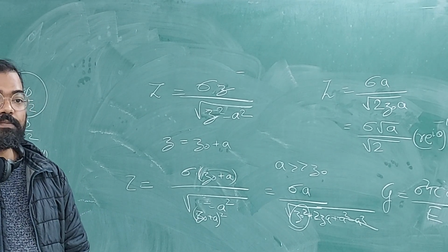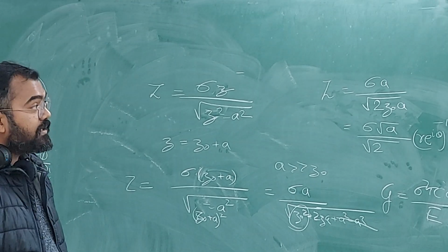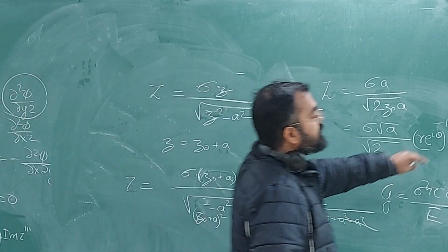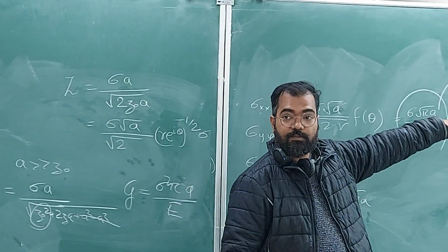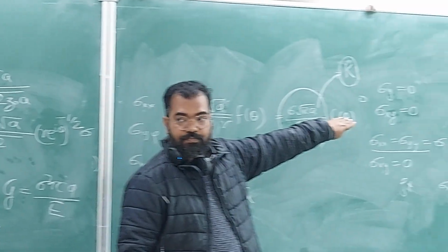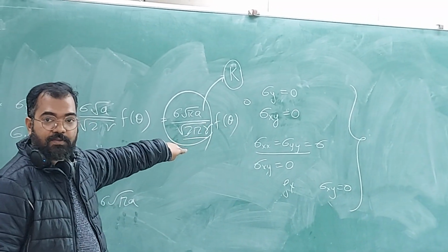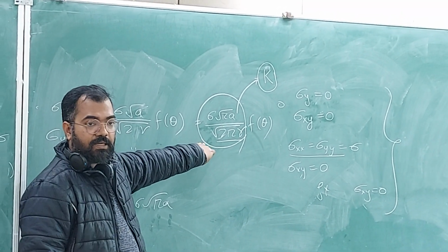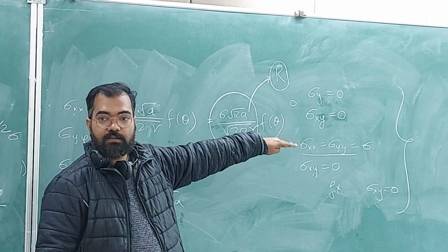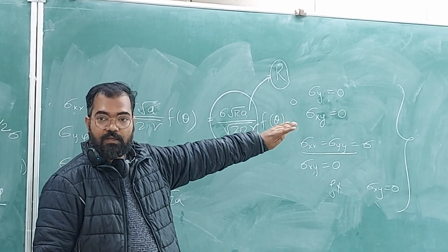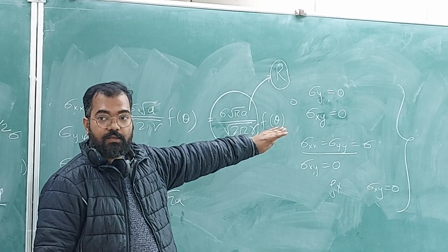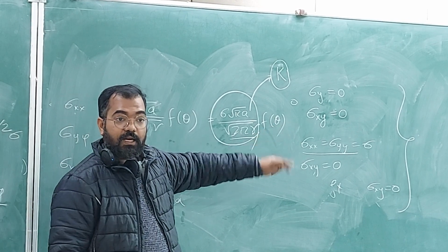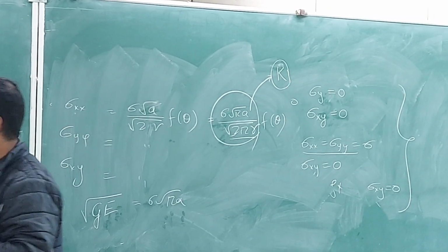Okay, and he comes up with the same expression, but the difference is that all the stresses also have higher order terms of r. So the first term matches with 1 over root r, but then you have higher order of r and derivative of the function. And that contributes to fracture mechanics later on.